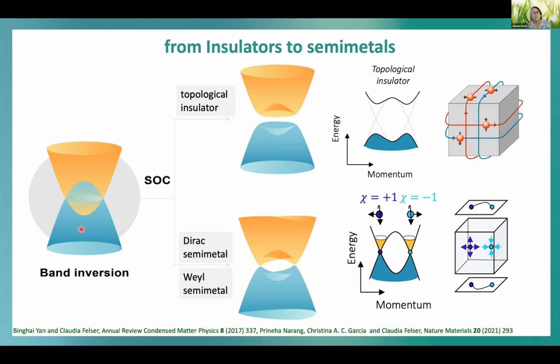So we have a conduction band and a valence band in this three-dimensional plot. And then we might have this overlapping area, the so-called nodal-line. And depending on the symmetry consideration and spin-orbit coupling, this can be a forbidden area, so forbidden crossing area. And so we end up with a band gap again, so parts of the conduction band and the valence band and vice versa.